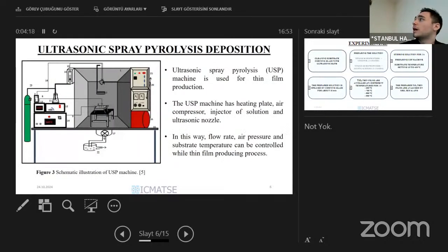I will talk about our technique, ultrasonic spray pyrolysis deposition. You can see a schematic illustration of the USP machine. We have four main parts: one is the heating plate, the other is the air compressor, another is the injector of solution, which feeds the solution to the ultrasonic nozzle, and the ultrasonic nozzle itself. Using these parts, we can set up the flow rate, air pressure, and substrate temperature, so we can control that while doing our experiments.